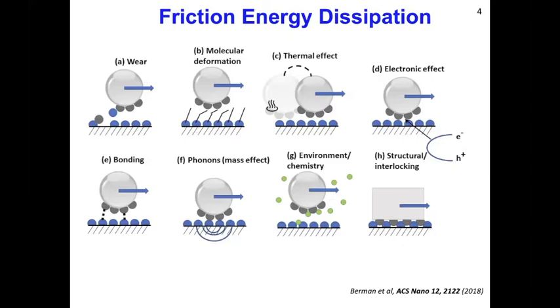And finally, one of the basic concepts that was specifically used for understanding how we can achieve superlubricity is structural interlocking. When you have good commensurate systems and they have these structures coming together, you have pretty high friction due to the locking of the systems. If you have a mismatch of these two sliding surfaces, that allows us to avoid the interlocking and thus to minimize the friction.